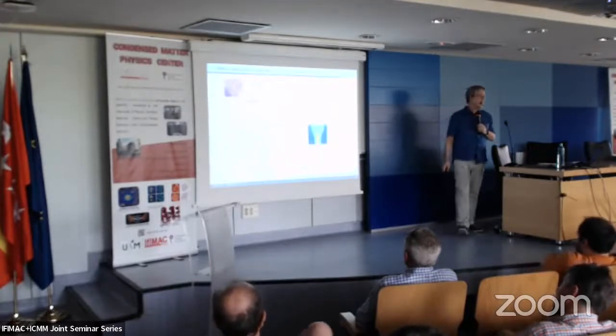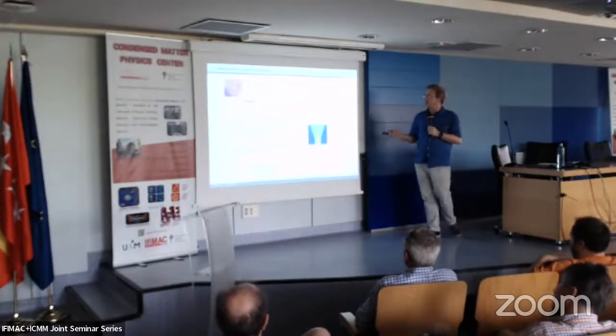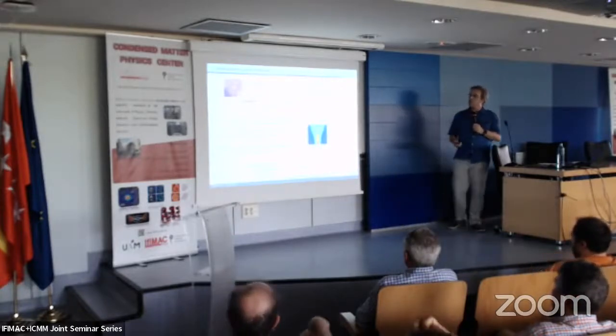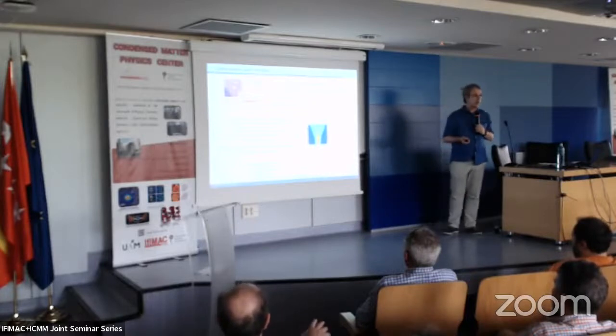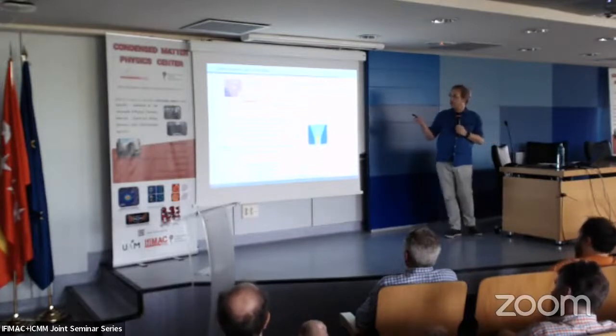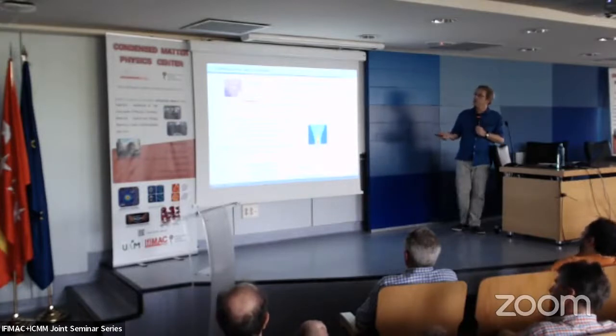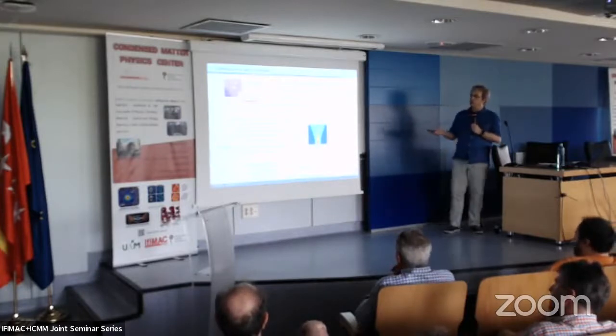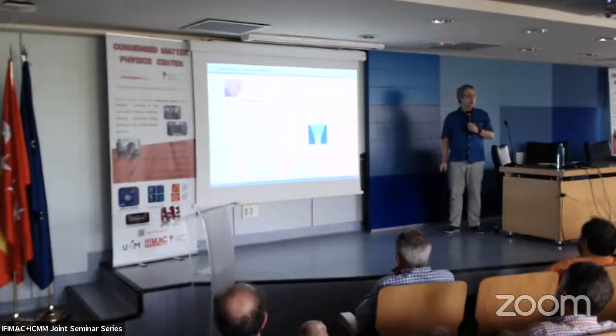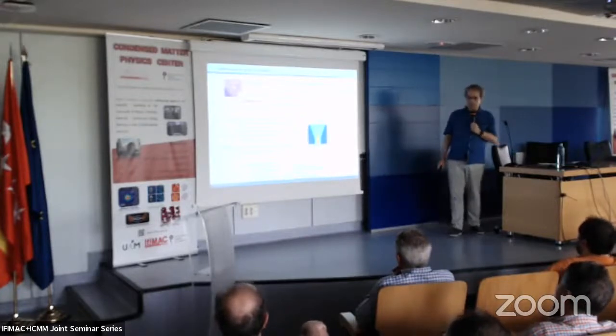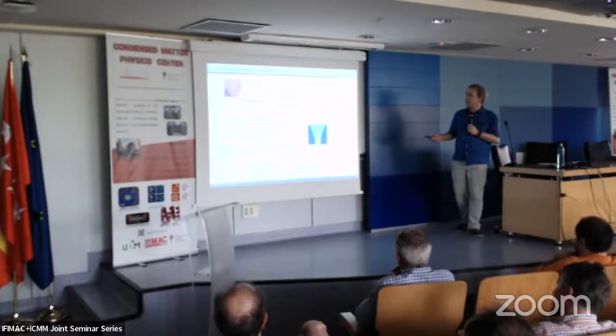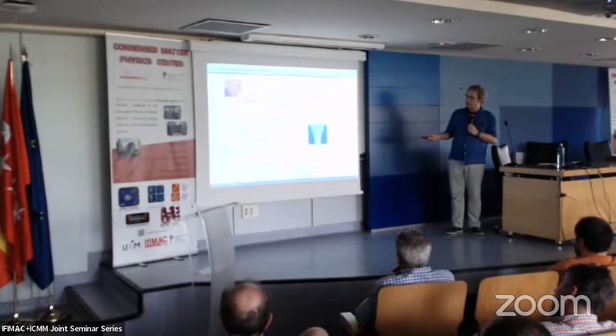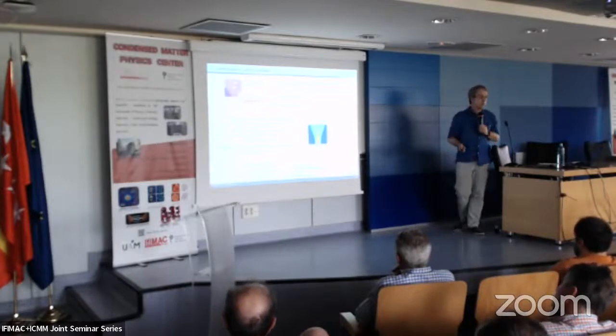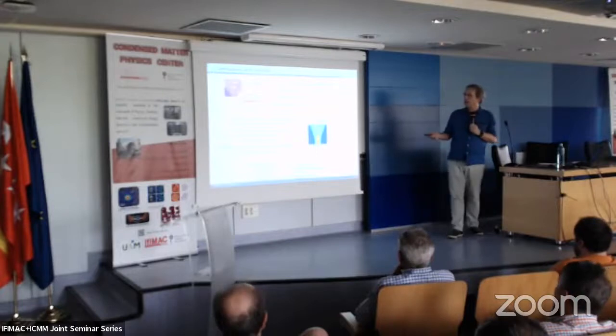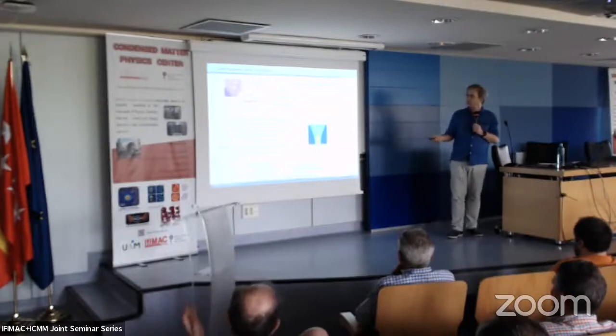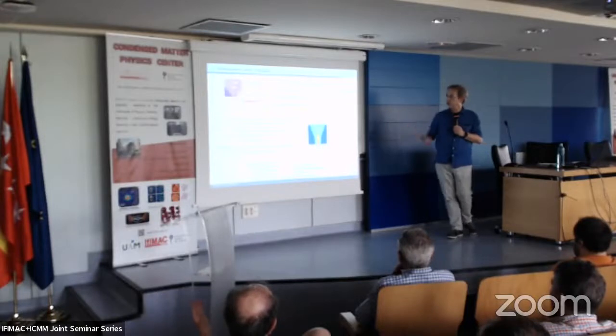So to conclude, these two materials, gallium selenide and boron nitride, show effects of strain. We have seen a single photon emission in this gallium selenide, and we'll try going on searching for more candidates for this emission. In boron nitride, we've seen that we can manipulate the emission, concentrate it at the surface, and make a tuning within certain limits.